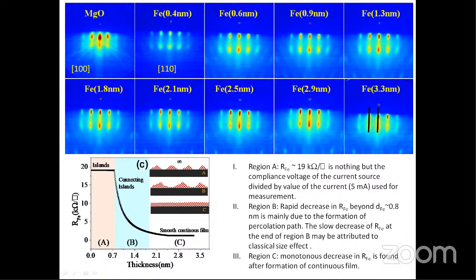This is the line profile of all the RHEED images along the horizontal direction, and this is the zoomed area of this yellow marked rectangle. One can see a slight change in the peak position of MgO and Fe as the Fe film thickness changes. This says that there is a slight change in the lattice parameter of MgO and Fe film. And the Fe film grows according to the epitaxial relation. This relation means that the Fe lattice is sitting on the MgO by rotating 45 degrees.